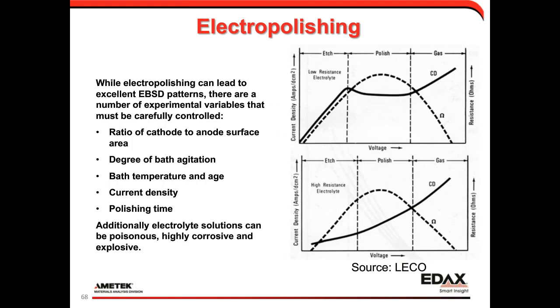And so while EBSD can give great results, there are a lot of variables that need to be controlled: the surface area ratios, bath agitation, the temperature and the age, your current density, your polishing time. And you can see on these curves, depending on which solution you use, you have to make sure you get in the right regime so you're polishing and not etching and not in a gas regime.